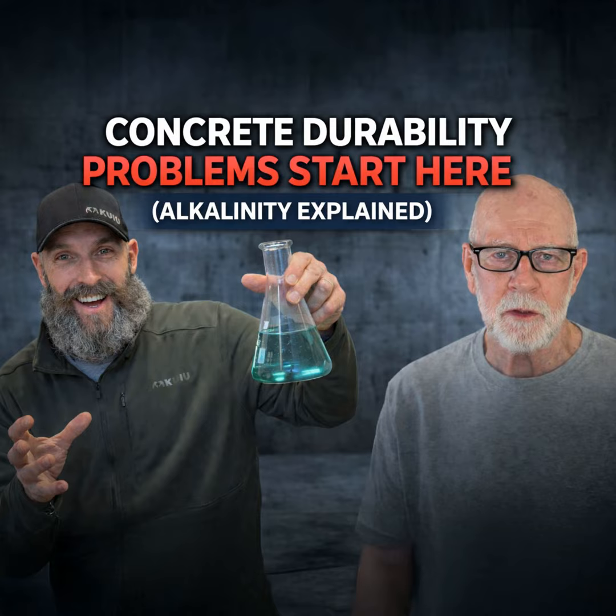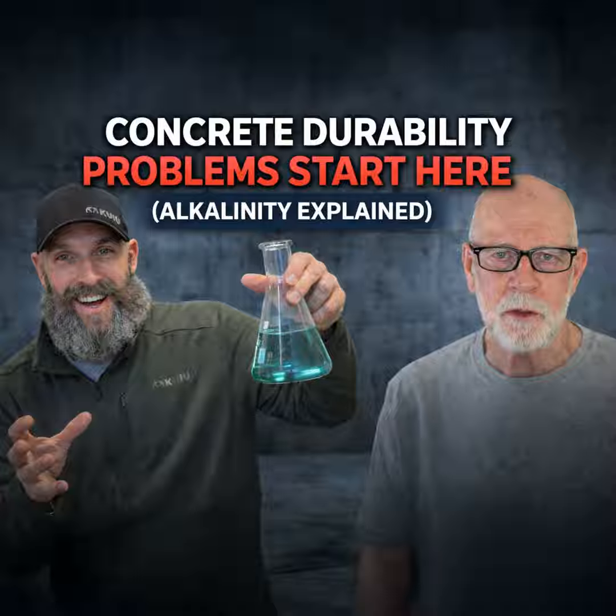Right. Well, couldn't you just solve the problem by putting a sealer on it? No. Why is that? Because the sealers will wear out. And for the most part, they can actually create more problems because with the free porosity and permeability of the concrete, you can get an alkaline buildup behind them. Salts come in, and the salts have considerable hydraulic pressure.